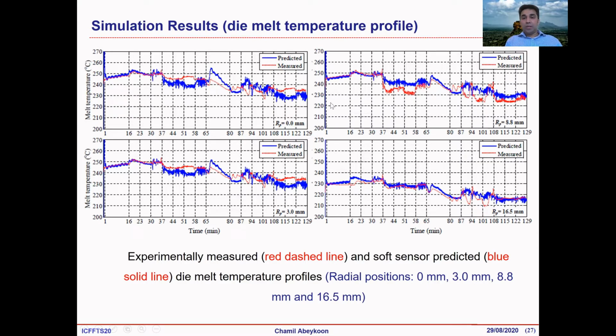But please look at this value here. You can see that value is really high. It's 250, 250. If you look at the full scale reading, this prediction error is really less than 5% even. Okay, so our soft sensor is good in predicting the melt temperature profile at different radial locations. This is at the middle of the melt flow, and this reading is at 3 millimeters away from the middle, 8.8 millimeters away from the middle. This is a circular die, and this is 16.5 millimeters away from the middle. Okay, so it's good enough. So then our soft sensor is working fine.